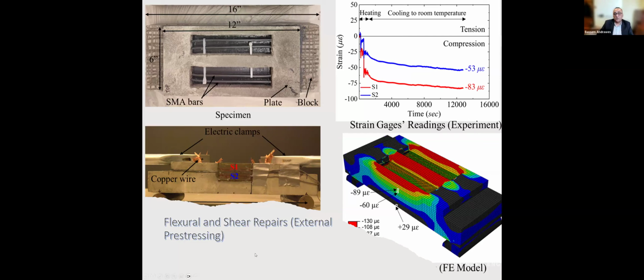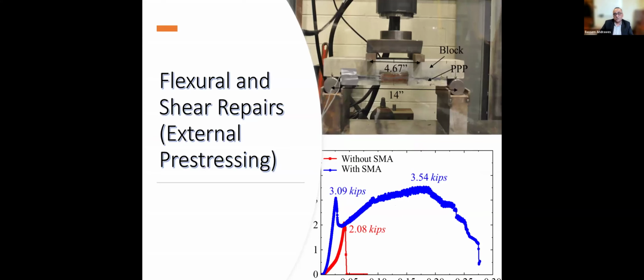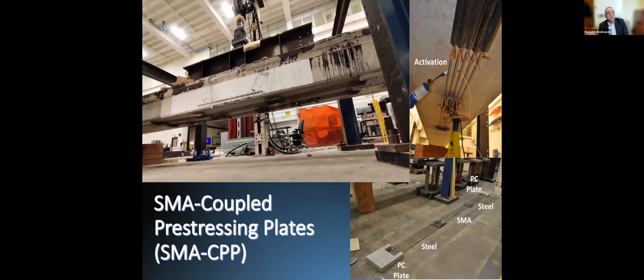When we activated the 4 wires, we found quite a bit of pre-stress transferring to the block underneath, and that was a very great outcome. We even tested that block in flexure, as you can see, and the strength and ductility both improved tremendously, showing improved behavior there because of the pre-stressing that's transferred. The most recent test we conducted was a large-scale test using this same concept with some variations. It's called the coupled pre-stressing plate, or the CPP. And this, I would say, is the first test of that size, that scale, using SMAs done in the US.